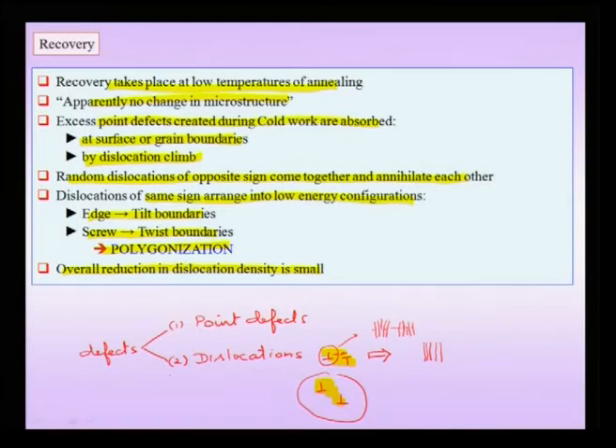boundaries, or dislocation climb can lead to it. Suppose I had a dislocation here and there are some excess vacancies here. These vacancies can come and sit at the base, that means the atom can come here and fill up this space. So, in that process now my dislocation has gone up one level. So, this can be the climb process by which vacancy concentration will come down. Of course, the opposite will take place if a self interstitial diffuses to the core of the dislocation.